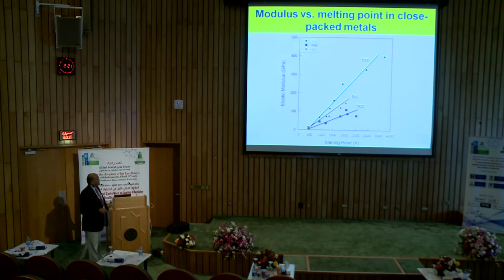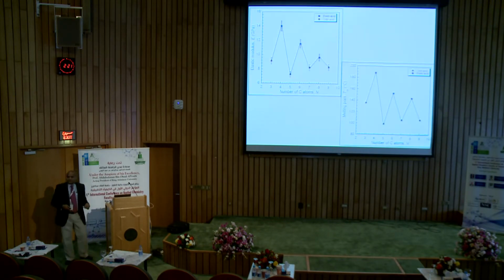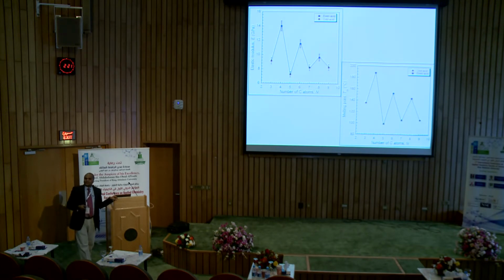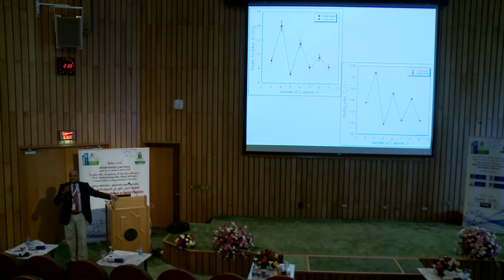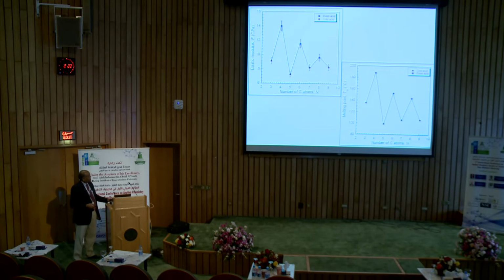So now, if I examine this, the elastic modulus also varies the same way, and this is the elastic modulus as a function of the number of atoms. You can see that when it is odd, it's low, and when it's even, you get high. So you get exactly the same alternation in the elastic modulus as in the melting point. This is the melting point, so you can see that they vary in exactly the same way.